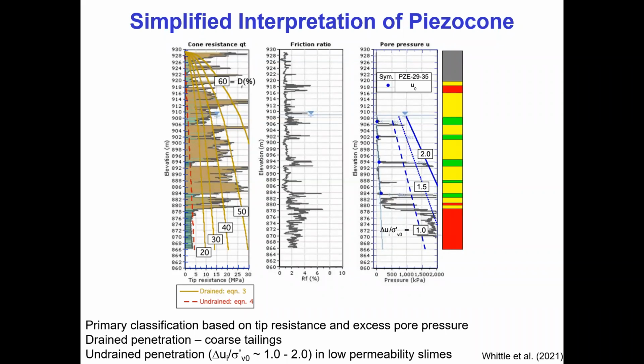What we did instead is we said, let's put on the maximum amount of fine material in this mix. So the yellow layers on the right represent where we're very sure we have a coarse material with few fines. The red material is where we think most likely we have some slimes. And the green is where we think we could be in that fine fraction from the deposition. And we went around all the piezocones looking at things this way.